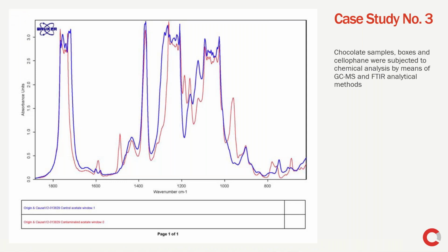Our analysis was done using a method called FTIR, and in this method, you obtain a spectra. The blue spectra in the image is for the good chocolate, and the red one is for the contaminated chocolate. Each peak on this graph represents a chemical compound, and some of the compounds identified in the red spectra belong to the solvents that I mentioned earlier.